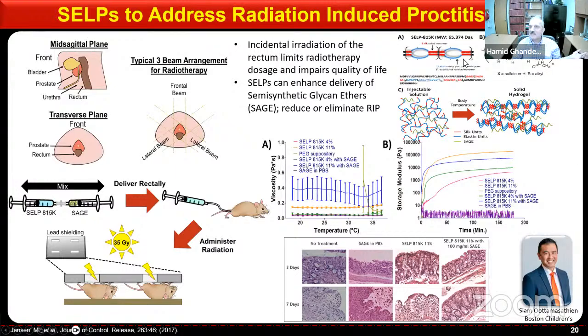So what we did was mix our silk elastin block copolymers with these GAGs. We looked at their viscosity, we looked at the storage modulus, and we came up with a specific sequence of these polymers, which I'll show you later, which is SELP 815K, that when mixed with these GAGs and delivered rectally, has enough residence time to reduce radiation-induced proctitis. That's the general idea, and we demonstrated that by histology.